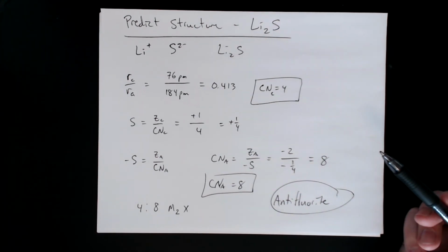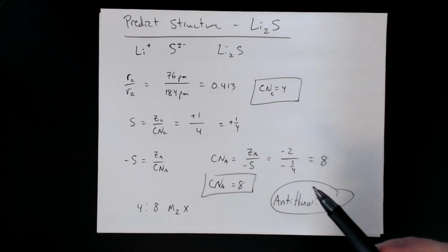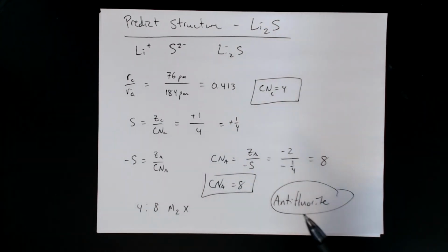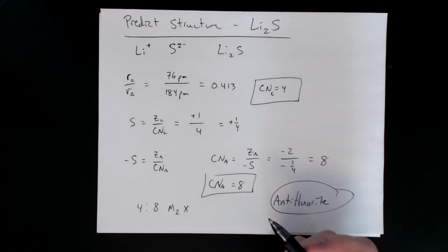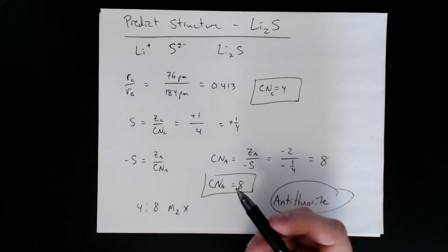I will caution you though, a lot of these, if you go through various compounds, covalency matters, right? So that can affect the results, and so you might not always get what you expect. And also looking at the values for cations and anions, you're going to find that the radii change with respect to the coordination number itself.